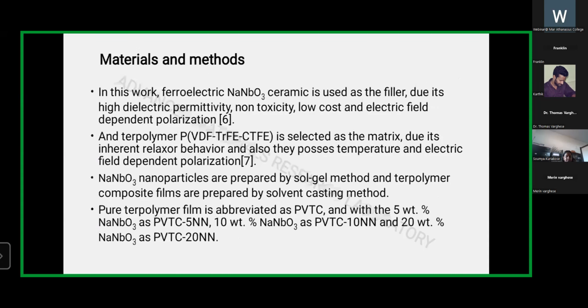Coming to the materials and methods I adopted, I selected sodium niobate ferroelectric as the filler due to its high electric permittivity, low cost, and non-toxicity. And mainly it has electric field dependent polarization. Coming to the polymer part, the terpolymer PVDF-TrFE-CTFE is selected as the matrix due to its inherent relaxor behavior. They also possess temperature dependent and electric field dependent polarization that can be used for harvesting energy.